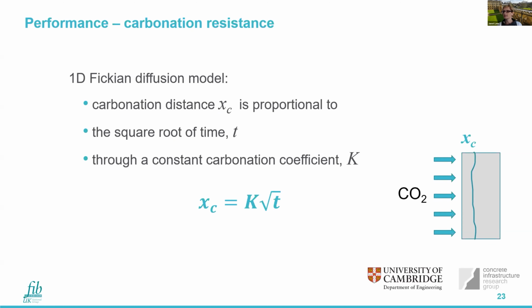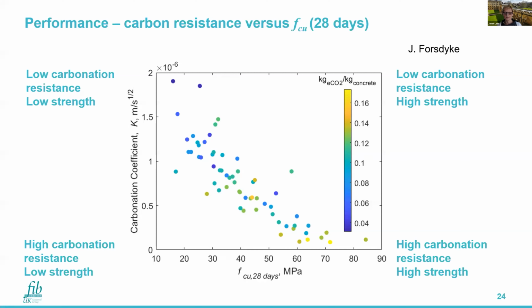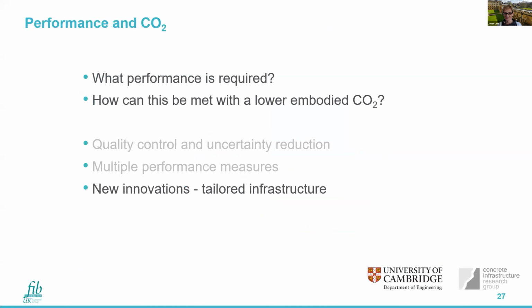So again, we could work back to find what carbonation coefficient we need. For the purpose of this, I've picked one, which is then a horizontal line of some description. And then we can also put on our strength. So now we have a strength and a carbonation resistance. And then within that space, we'd be looking for the lower carbon options, which would be the more blue colors. So once we start looking at multi-criteria performance, we have to do it in a very intelligent way, because we are trading off different material resistances, and also the overall structural form itself, amongst many other criteria.